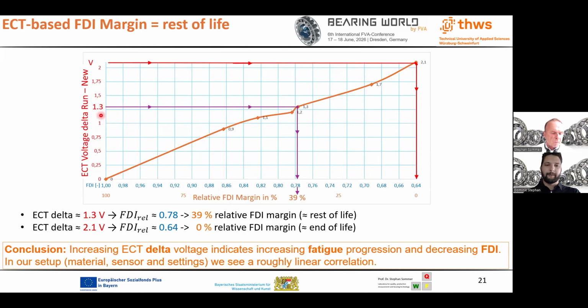At the same depth, the FDI evaluation gives an FDI relative of approximately 0.78. In our setup, this corresponds to a remaining FDI margin of about 39%, which we used here as an estimate for the remaining service life margin. If the ECT delta increases to approximately 2.1 volts, the FDI relative would reach a critical value of 0.64. In this interpretation, the remaining FDI margin reaches 0%, which corresponds to the end-of-life condition.